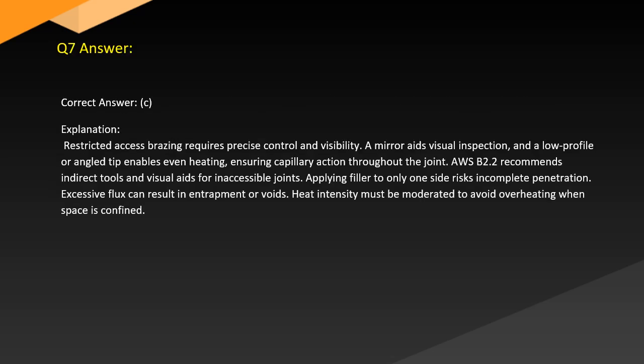Answer. Correct answer: C. Explanation: Restricted access brazing requires precise control and visibility. A mirror aids visual inspection, and a low-profile or angled tip enables even heating, ensuring capillary action throughout the joint. AWS B2.2 recommends indirect tools and visual aids for inaccessible joints. Applying filler to only one side risks incomplete penetration. Excessive flux can result in entrapment or voids. Heat intensity must be moderated to avoid overheating when space is confined.